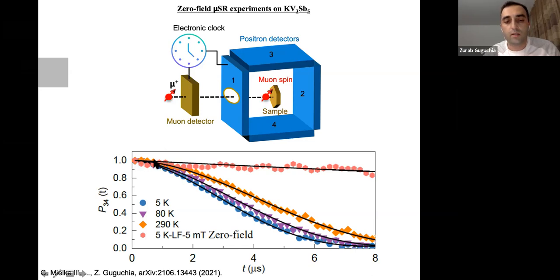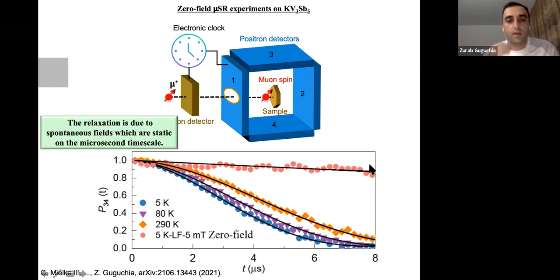And then we apply a small longitudinal field. Here we have the muon spin, which is rotated by 60 degrees with respect to the c-axis, and then we have these 4 different positron detectors. If you apply a magnetic field along the spin polarization, you can completely decouple the relaxation rate. And this is a signature for static internal fields on the microsecond time scale. So we don't have fluctuations, but we have really static internal fields at the muon site.